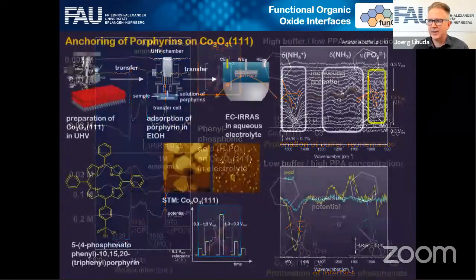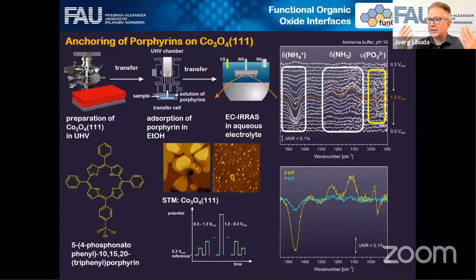It's very stable. And then the holy grail is, of course, to use that knowledge then to understand really functional films. So for instance, we're looking at porphyrins on this oxide surface. Porphyrins are big molecules like you see here. So they have this core where you can put metal ions and then they can perform all kinds of functions, catalytic, sensor functions, all kinds of things. And you can attach these molecules with the same linker group, again, with this phosphonic acid. So that's what we do.